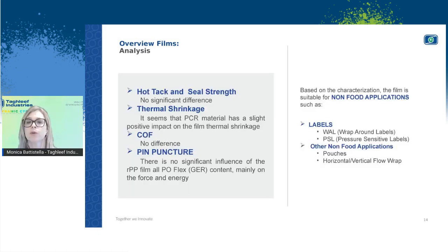So all in all, what could we identify for this film? Based on the assessments that we carried out, which are the assessments that we would normally carry out on all our portfolio just to validate and make sure that the quality is okay and suitable for the subsequent converting step, we validated that for hot tack and seal strength, there was no significant difference between material with recycled content and material with zero recycled content, so based totally on fossil virgin material. Thermal shrinkage demonstrated that even PCR material had a slight positive impact on the film thermal shrinkage. The COF had no difference at all.